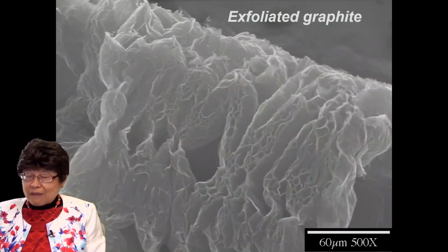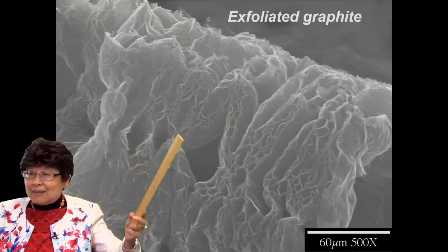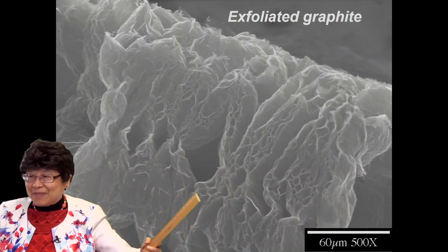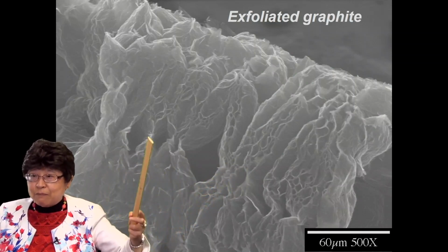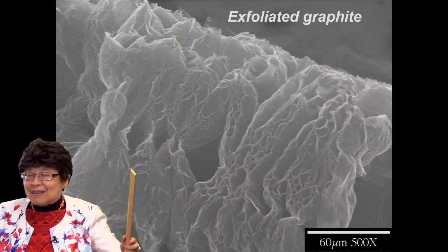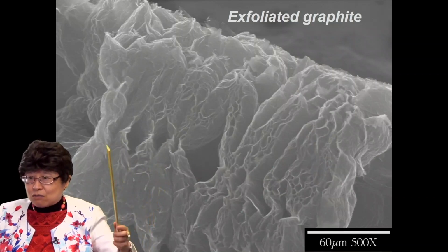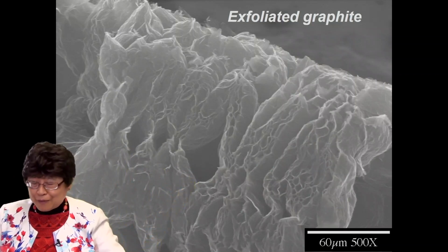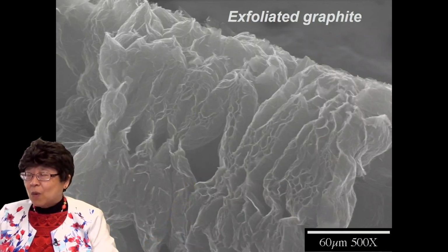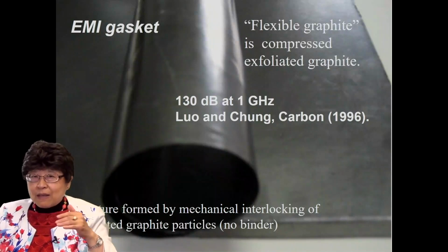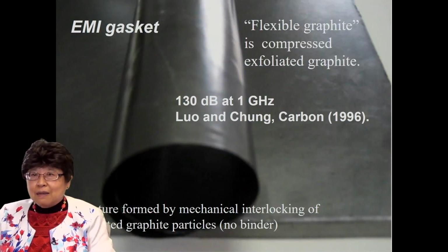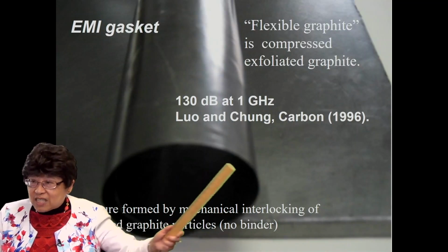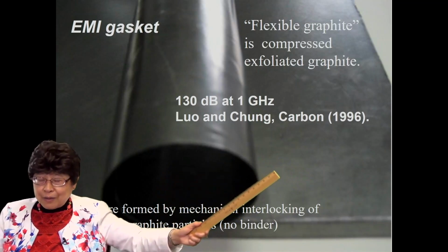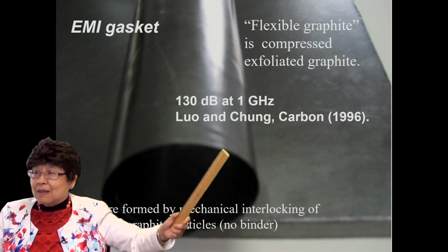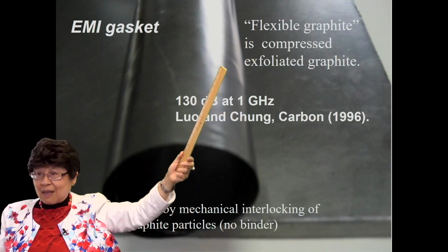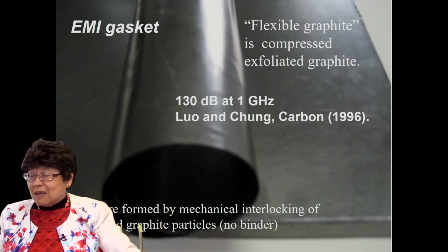There is a form of graphite called exfoliated graphite, and it's puffed up. It's like having a cellular structure, a lot of pores inside. Because of that structure, it's got a lot of surface area per unit volume. And if you have a pile of such exfoliated graphite and compress that, you have mechanical interlocking among the different pieces of exfoliated graphite so that you get a sheet without the need for any binder. And this sheet is flexible, so it is called flexible graphite. It's simply compressed exfoliated graphite.